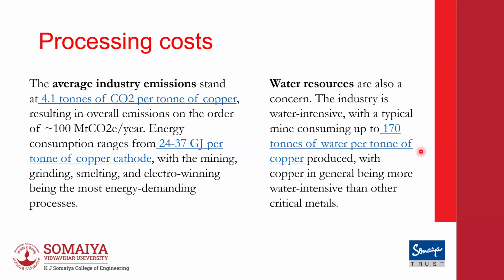Now, in all these processes, I am heating, holding, waiting, pouring, all done at high temperature. The melting point of copper is 1083 degrees Celsius, and most of the furnaces in copper run at temperatures around 1350 to 1400 degrees Celsius. The average industry emissions are around 4.1 tons of CO2 per ton of copper. So this is the amount of CO2 generated if I want to process 1 ton. And this is the amount of energy if I want to make a copper cathode, which is my final product: 24 to 37 gigajoules.